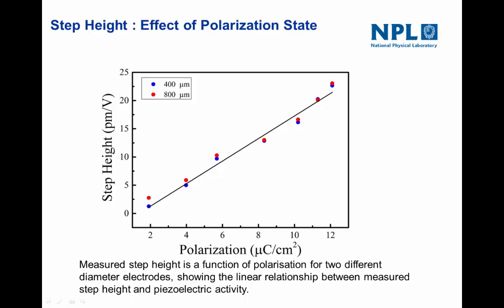Comparing to the center displacement results (dotted lines), those get values ranging from 30 to minus 170 — whereas the step height is pretty constant. To confirm that what we're measuring is a material parameter rather than an artifact, we polarized the material to different levels — effectively changing the piezoelectric coefficient — and repeated the measurements. The result is a nice linear plot between the polarization level measured using a PE loop and the step height, going through zero, and it's linear for both the 0.4 and 0.8 millimeter diameter pads. We can therefore be confident this is actually a material parameter.